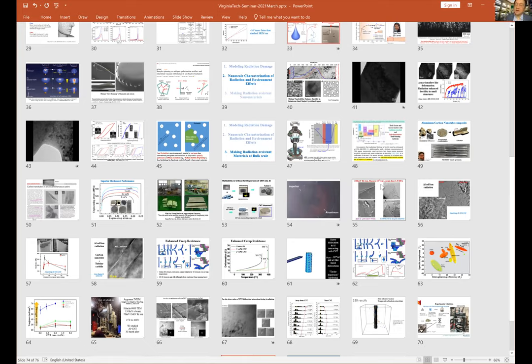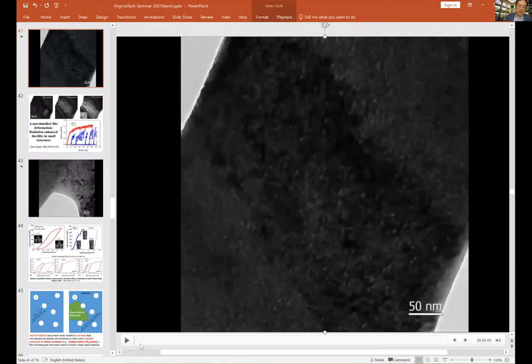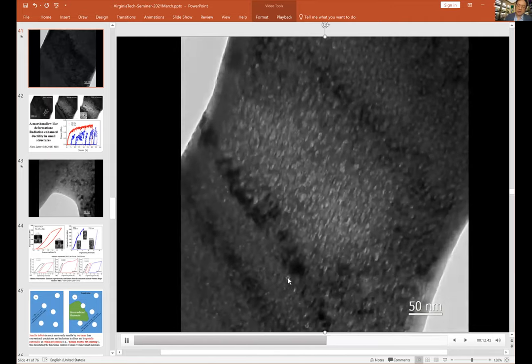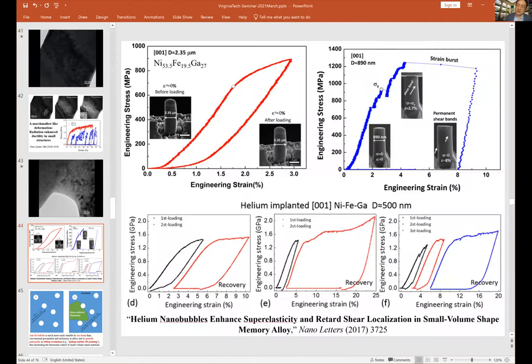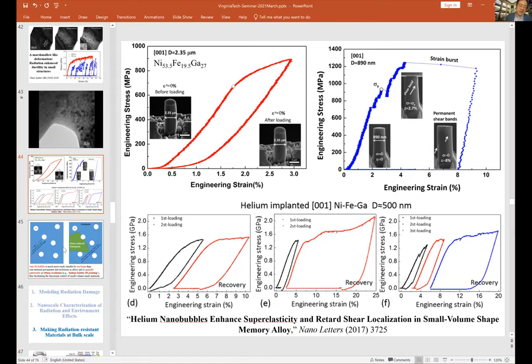Yes, that's a great question. Thank you. Indeed, that's the problem that I've been thinking about for a long time. Today, that connection is very vague and haphazard, but we do have a few success examples. For example, sometimes you get surprises at the nanoscale. This experiment showed, almost like proof by exclusion, that the grain boundary is very important. The helium tolerance largely comes from the grain boundary. And if you can eliminate grain boundaries, then you have a chance to reduce the sensitivity of this helium vulnerability.